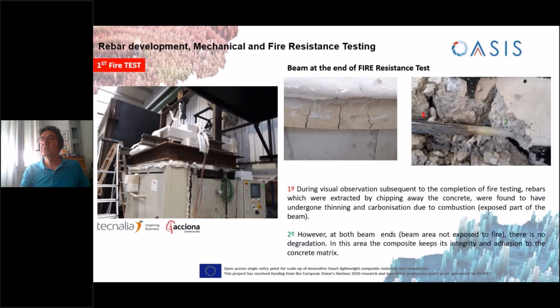Finally, fire-resistant tests were performed at Tecnalia facilities under sustained flexural loading until failure. These pictures were taken at the beginning of the test, the picture on the left, and at the end of the test, the pictures on the right side of the slide. From these pictures, very valuable information can be extracted, and it will help to further develop the final solution, thanks to the collaboration between Fraunhofer ISC, Fraunhofer IGCV, Tecnalia, and Acciona.